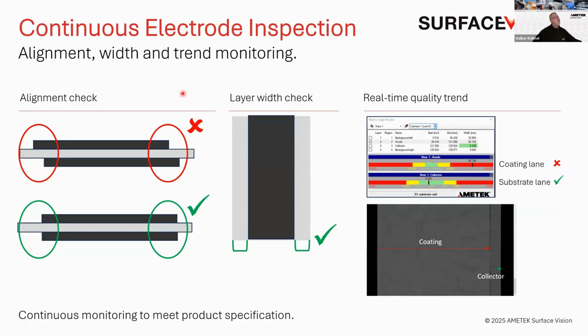When we have, let's say, top and bottom view inspection, we do not only measure the top surface and the coating or substrate. In this case, we will also do an alignment check where we tell the system where the edges are, or where the coating is on the substrate between top and bottom. So here, for example, there would be an offset and it would fail the alignment check. And if this is the case, we will warn you. This type of request is mainly on the coating process because here you can directly influence it: if you see that alignment is running out of your spec, you can do the correction.